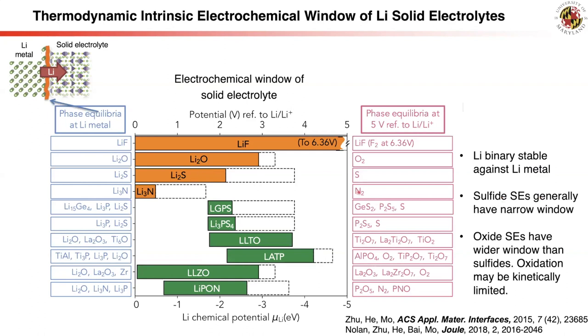We use the same computation methods to evaluate the thermodynamic intrinsic stability window of many lithium solid electrolytes. Sulfide solid electrolytes all have a similarly narrow electrochemical window, limited by the reduction of phosphorus and the cation, and the oxidation of sulfur.